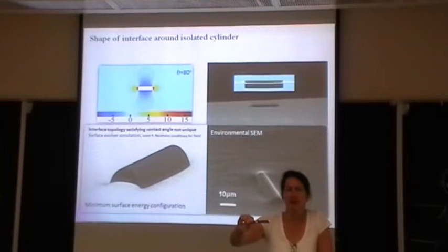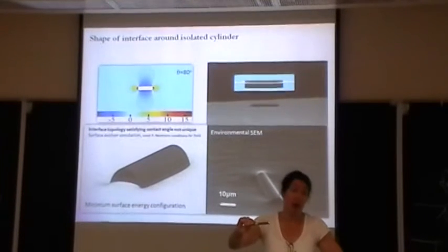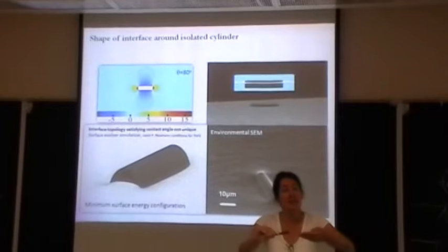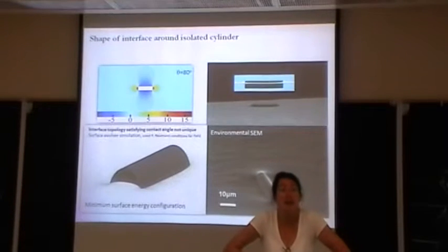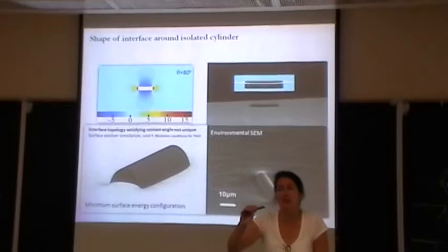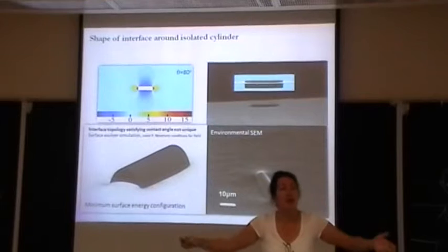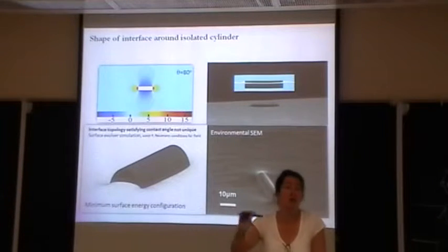If we put surfactants in the system, and they adsorb non-uniformly on that particle, they can create patchy wetting. And we'll always have a quadrupolar interaction. But the near field things that were the signatures that made these things know, we're cylinders, we like to come end to end, those could get messed up by patchy wetting. Okay. But the interactions would still occur, but now they would not just be signatures of shape, they'd be signatures of shape plus patchy wetting.